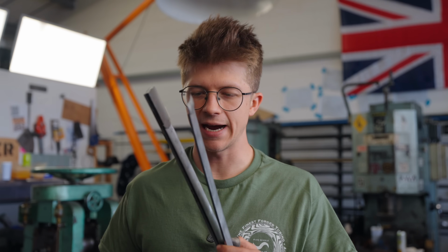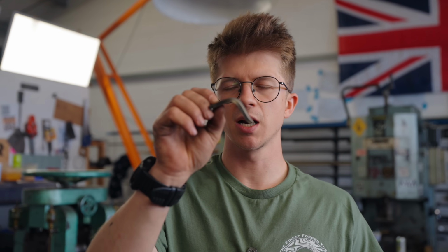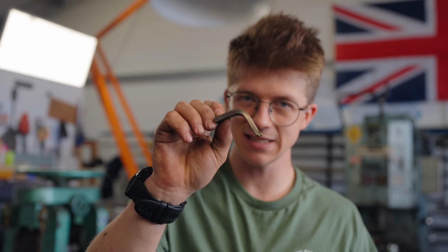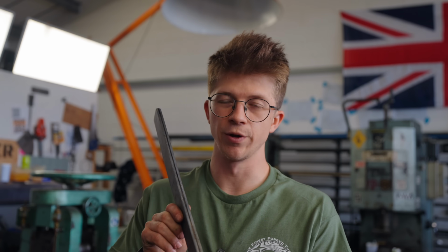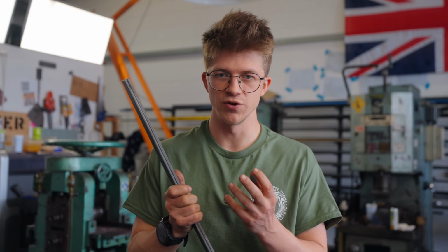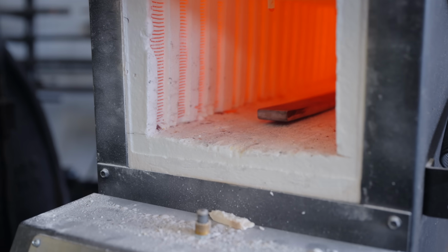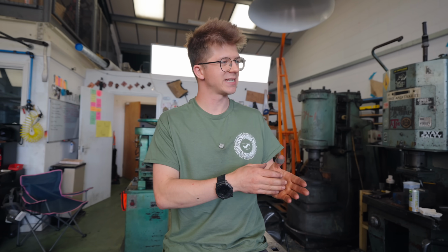All that I can think to do now is, considering the really remarkable success we had rolling this piece's thickness down, instead of trying to mill my thickness down on this, maybe we will try and roll the thickness down. It's possible that that rolling is enhancing the bond and making the bond stronger. Again, I can only do so much of it because we only got so much furnace length to play with. But I think this is my last hope now. Roll at 850 to reduce the thickness, get it close to katana thickness, then put a bevel on it and hopefully test its performance and see, is it going to be enough?